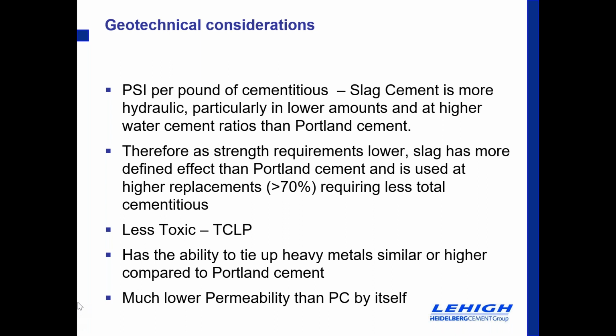after the application of this material underground, and it went something like this: you have solidified all of our sumps in our mine. What I'm saying is, whereas with more cementitious and no slag, just Portland cement, the material would work its way into the bottom of the sumps, and because it was in small quantities, it was just handled as a normal fluid. Slag cement changed that. Even at very, very small amounts, there was enough there for the cement to activate and solidify the slag. So we quickly realized it was working, but we needed to do something to keep the slag more in the chambers. And in this application, we just added a flocculant, so it settled out a little quicker, and we were able to keep more of the cementitious where we wanted it.